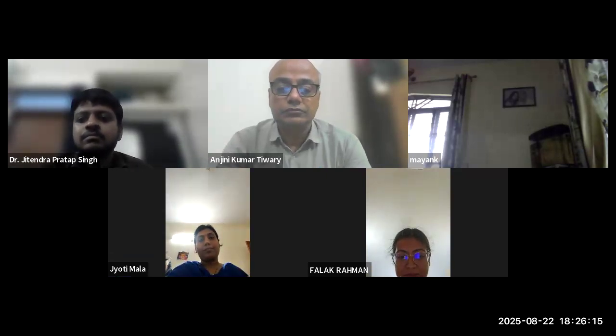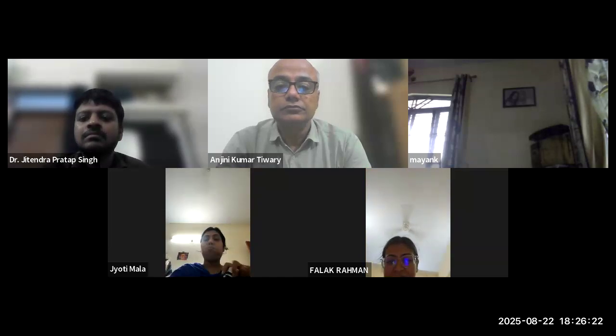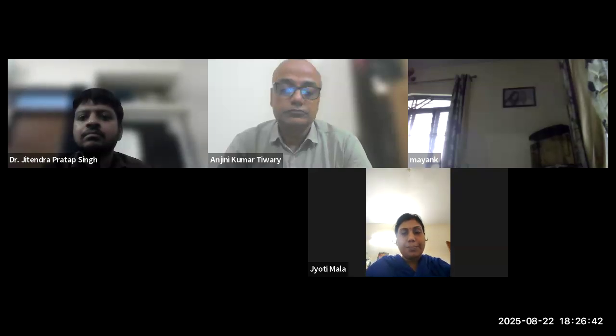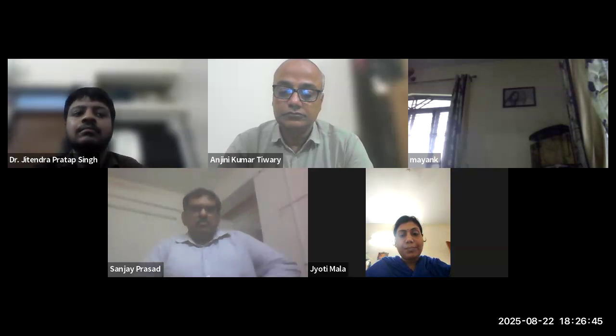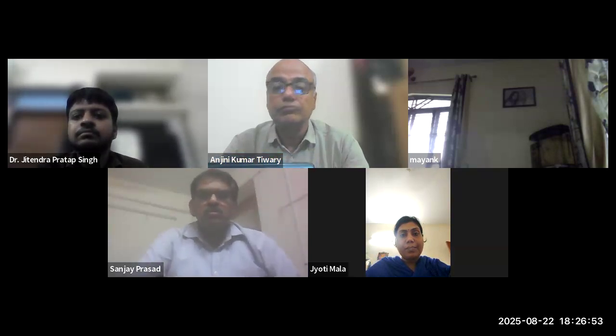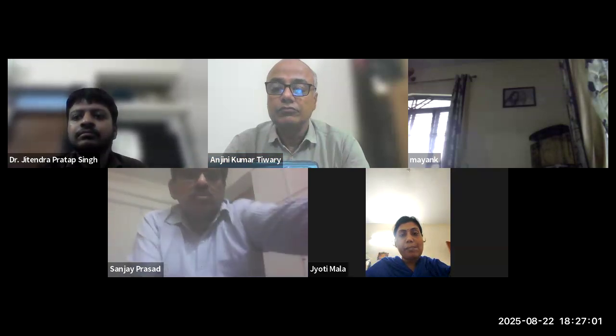See, the figure first shows that when a structure develops cracks by any chance, if this structure is made with self-healing concrete, in the first week its gap is like this, in the second week like this, and in the third week like this. It means in just 3 weeks, we can overcome the problem of cracks. But there is some limitation. At present, we have limited capacity: we can heal only 0.5 to 1 mm. It is of two types. In self-healing concrete, we use some bacteria in the concrete and some capsule-based elements in the concrete.